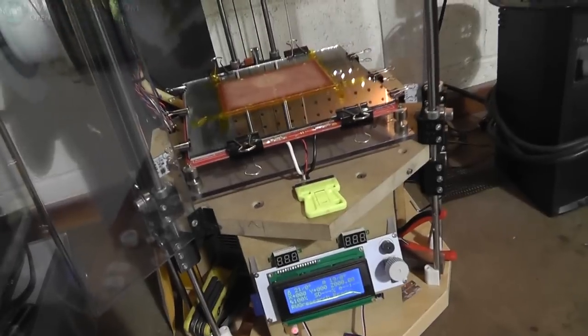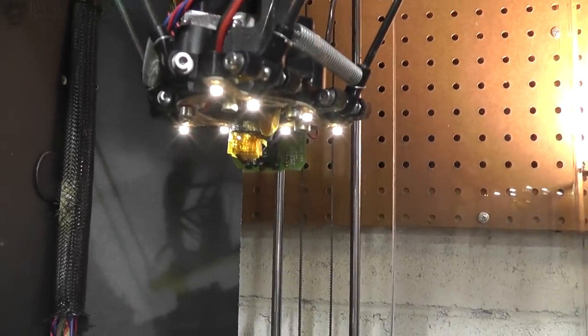So here I actually went and tested each one of these - again that's in another video - and I am actually thinking that around 238 to 242°C is a great temperature for my hotend. Now every hotend is going to vary, so everybody's going to have a different opinion on what they like on their printer.